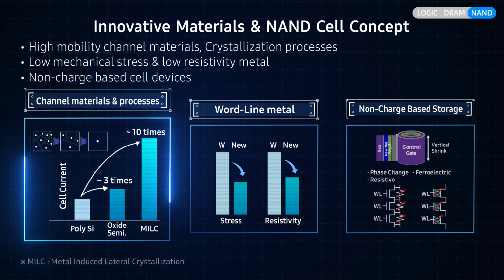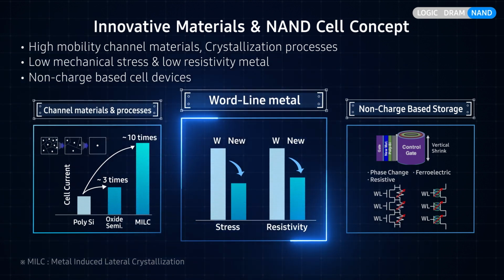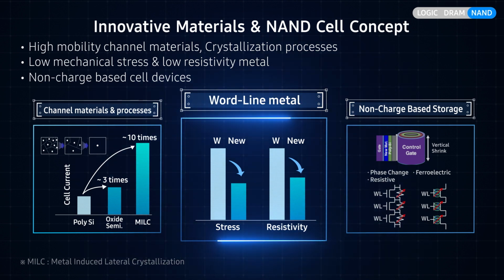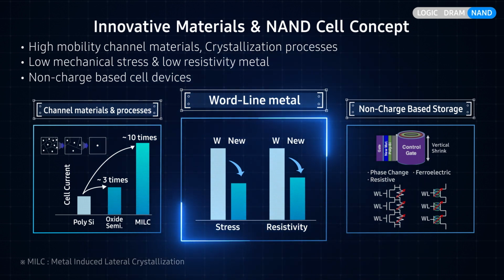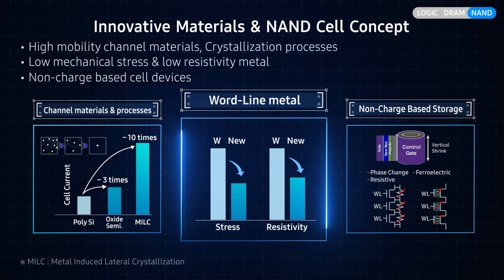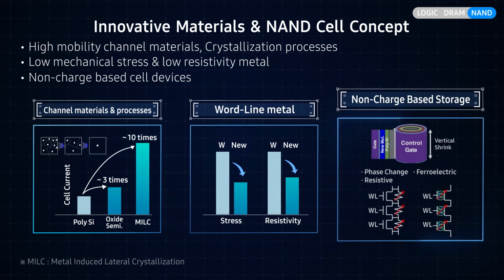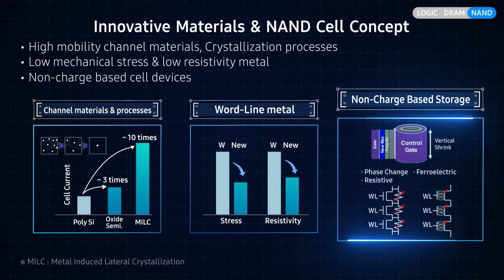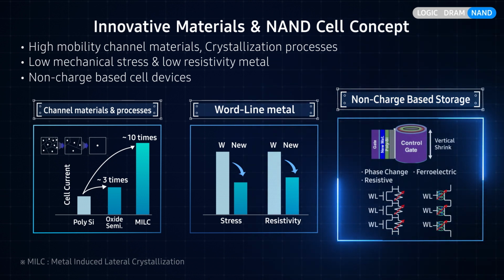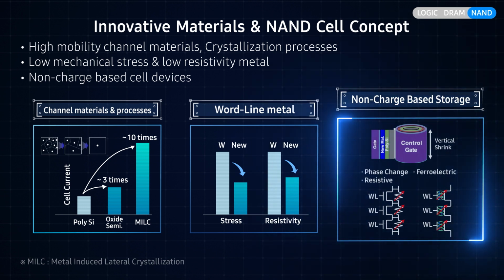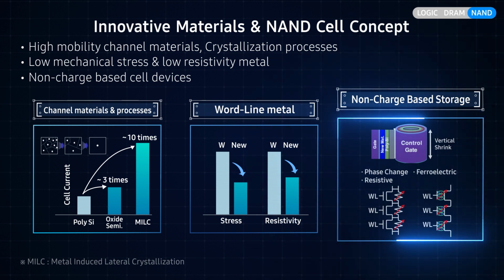On the other hand, in order to improve the mechanical stability, we need low stress and low resistivity metal films without sacrificing excellent step coverage. Eventually, we may pursue to slow down the total stack height increase. To this end, we need to decrease the operation voltages, such as program and erase, by adopting innovative non-charge-based storage devices, such as ferroelectrics or resistive memory devices. In summarizing regarding future flash, innovative cell structures, advanced process, new materials for channel transistors, and innovative non-charge-based memory devices will enable flash to stack over 1,000 layers and beyond.